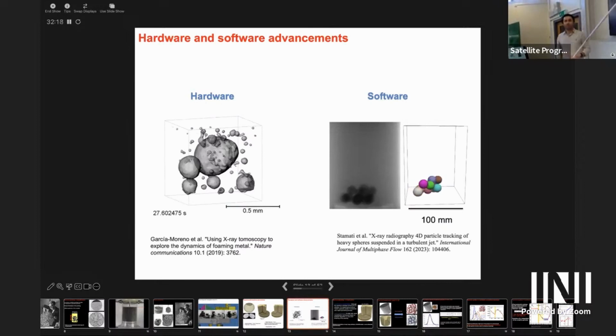Okay, so I didn't really run you through all the details of tomography. So you are supposed to take around 10,000 or so projections of the sample from different angles in order to reconstruct a 3D image. But here, using new algorithms, you can actually reconstruct a 3D structure using a single X-ray projection. Okay, so that will increase your temporal resolution by 10,000-fold. So, yeah. Provided you know that they're spheres. So you need, yes, you need to have some a priori information.